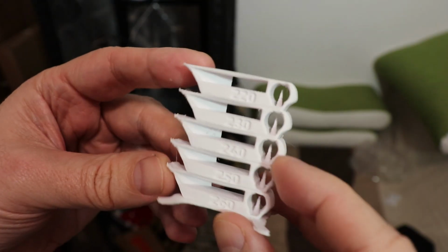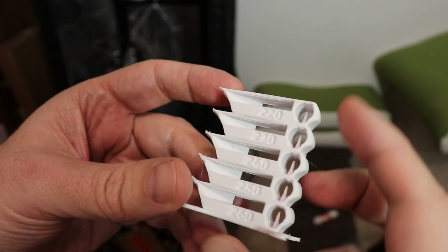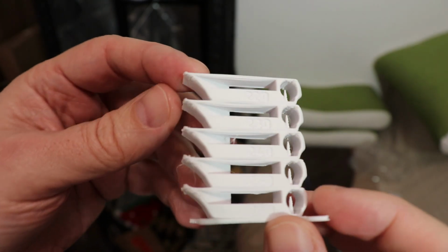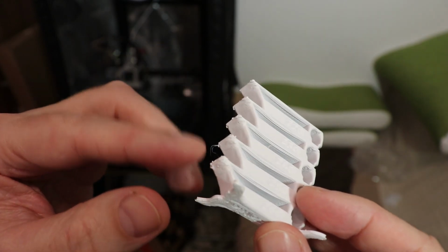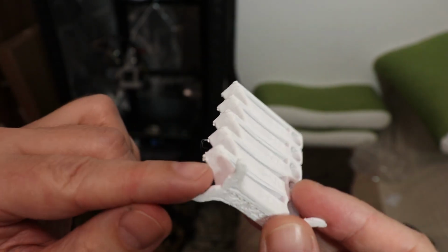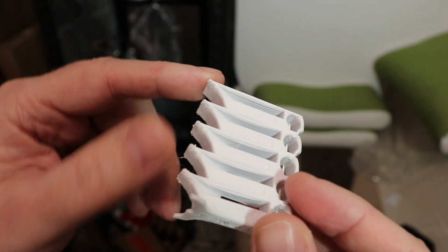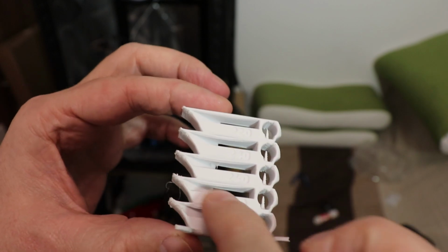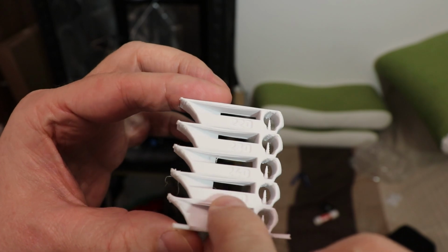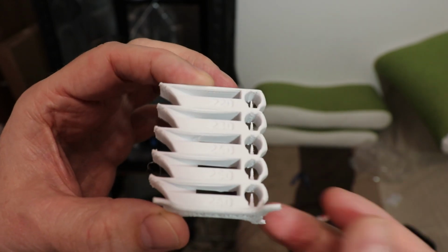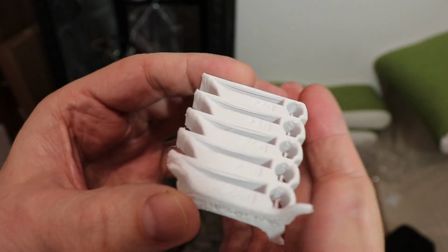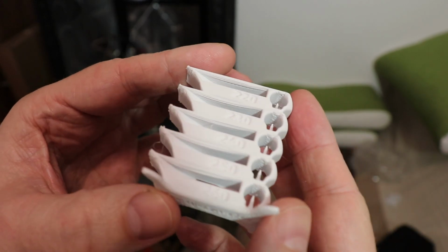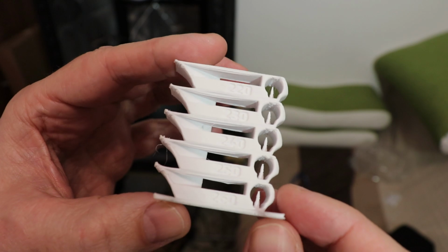And this is the temperature tower. Let's analyze it a little bit. There is no stringing at all. That's usually not even a problem with ABS. But the overhang, yes, because of very small part cooling, and this is a very bad overhang. And of course the best is at 220 degrees Celsius, but I think these three are quite equal, so probably my choice will be printing at 250 degrees Celsius to get better layer adhesion. And you can see the bridging is also very similar in all five cases.